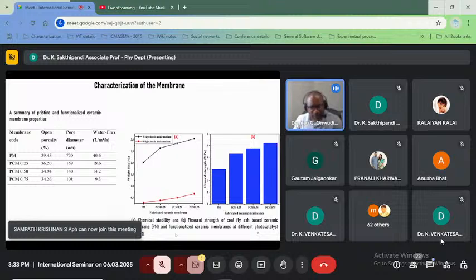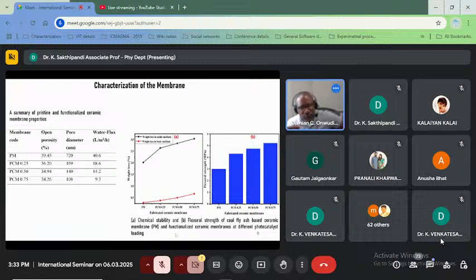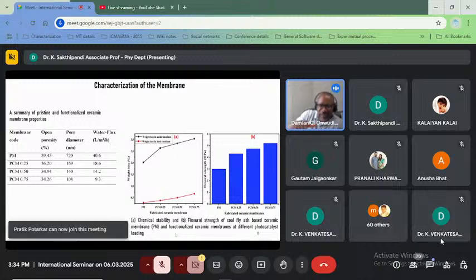All right, so what we did was to determine the pore diameter, the porosity, and the water flux of these ceramic membranes with respect to the functionalization. So as you go down, PM is the pristine material. PCM0.25 is pristine material functionalized with 0.25 gram. PCM 0.5 is the material functionalized with 0.50 gram of nanomaterial, while PCM0.75 is the ceramic membrane functionalized with 0.75 gram. If you look at the table, you see that as you increase the quantity of the nanomaterial, the porosity decreases.